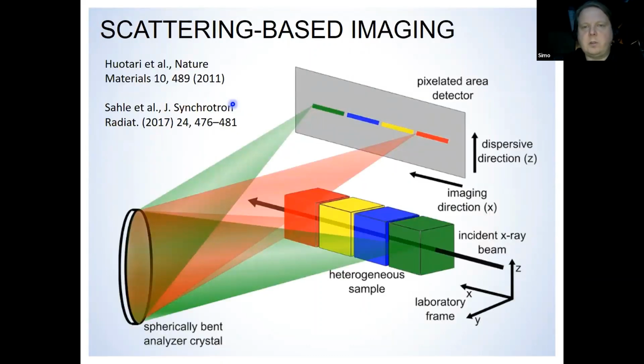So this shows a cartoon of the idea. An incident X-ray beam comes in through a sample that has several different kinds of structures. This spherically bent crystal analyzer is now the heart of the system. It selects the wavelength with electron volt or sub-electron volt accuracy, and then it focuses the radiation that it selects onto a detector. If you put a pixelated area detector here, it can discriminate the signal that comes from the green part, focused here, from the red part, which gets focused here. So this is a very easy way to do scattering-based imaging. It's dark field imaging in a way.